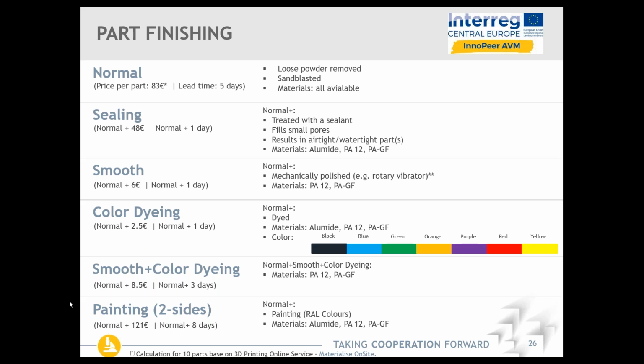What you have to take into the consideration when using smoothing on your parts is to avoid thin walls, because during this mechanical process they can wear or be damaged. Finishing allowance is recommended for this type of finishing process, and typically this is around 100 microns, so 0.1 millimeter. And you have to be aware of that. Using polishing on your parts will affect the edges of the part, which will be all rounded, so the part will not be as crisp as with normal finishing. The process is typically limited to a range of part sizes from 30 up to 200 millimeters.